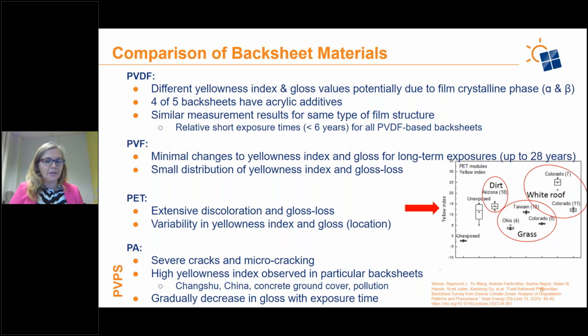So some observations that we saw in these modules: PVDF. Interestingly enough, we saw that they had alpha and beta phase in their crystalline phase. We were unable to identify if those were there prior at 0 age or if they changed during the course of the exposure time. For PVF, we had minimal changes to yellowness index or gloss over up to 28 years of exposure. In that case, we had a module that had been stored in a shed that had never, quote, been exposed outdoors, but had definitely had thermal changes because it had been sitting in a shed.